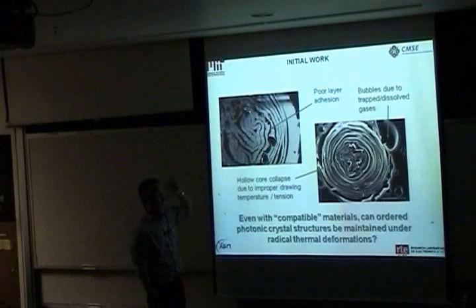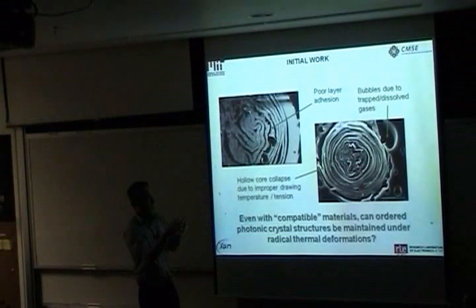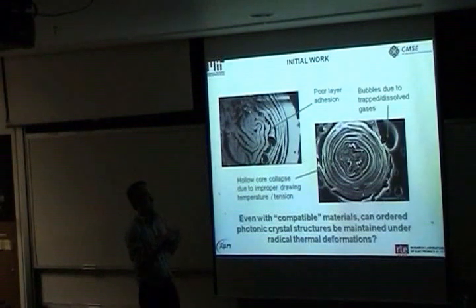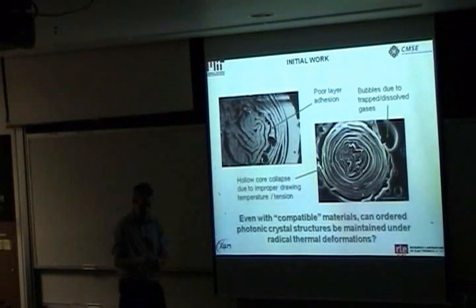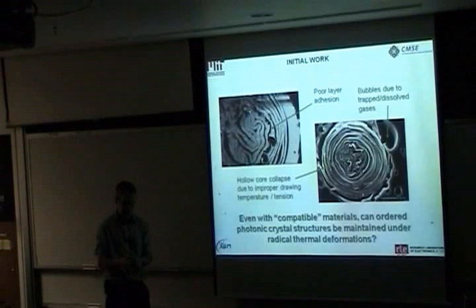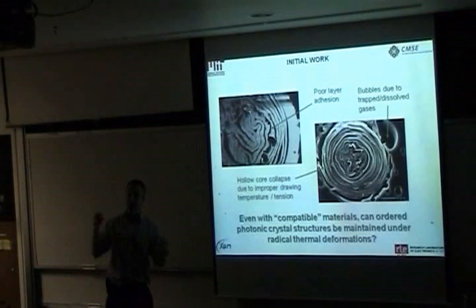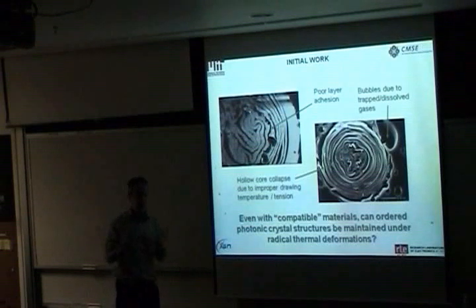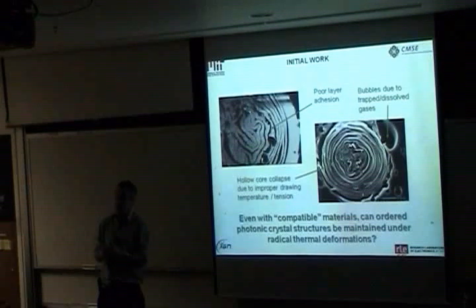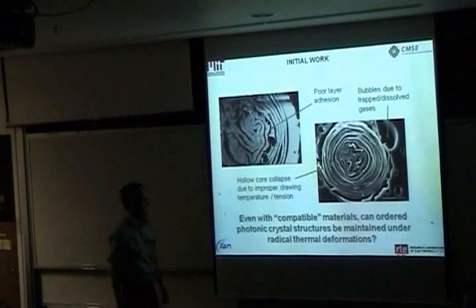And in particular, as you're starting to realize this approach, lots of things could and did in fact happen. Let's talk about some of them just briefly. One of them is you have this hollow core, and the hollow core is compressible. And obviously as you're drawing this thing down, the surface area associated with the hollow core is increasing. And one of the things this hollow core would love to do, being in a fluid state, is actually to collapse, because that would minimize the surface area and the surface tension.